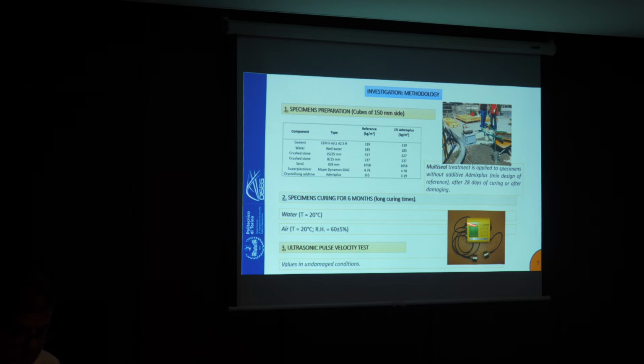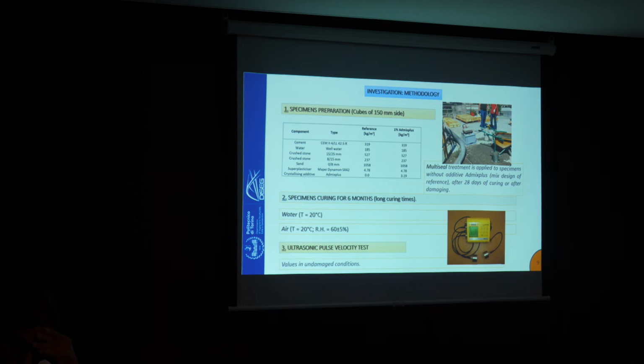And regarding the other case, the case of Multi-Seal, as I said, this is applied to an existing structure. So what we did is prepare a reference sample and then apply the Multi-Seal on this reference sample. You know that in an existing structure you could have two different possibilities. One, an undamaged structure, without the presence of cracks. And the second possibility is to have cracks, so a cracked concrete surface. So we test the two possibilities, applying Multi-Seal on undamaged samples and on damaged samples.